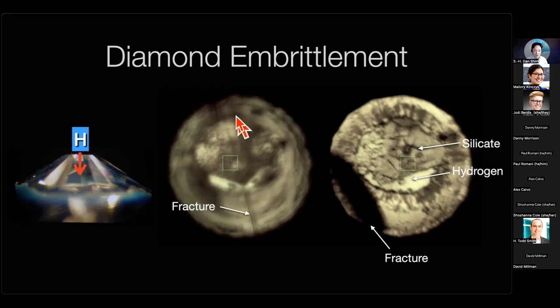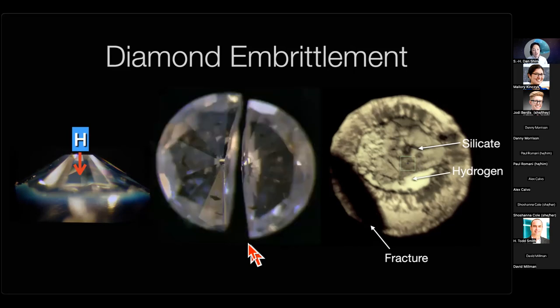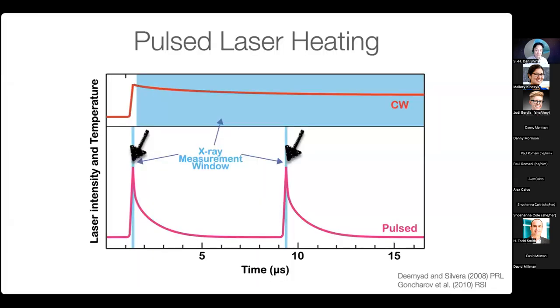And if you look at the middle picture, you can see that it is not focused. It's not because we want to blur the image, but because it is being damaged and slowly split under high pressure because of the hydrogen effect. You can in fact see a very sharp fracture going through the sample. And you will ultimately break or shatter diamonds in this way, which ultimately fails the experiment. And this normally happens during the experiment, and you know, we cannot really collect any meaningful data. So the important experimental challenge that we need to solve to be able to study hydrogen under very high temperature conditions is to prevent this type of experimental problem.